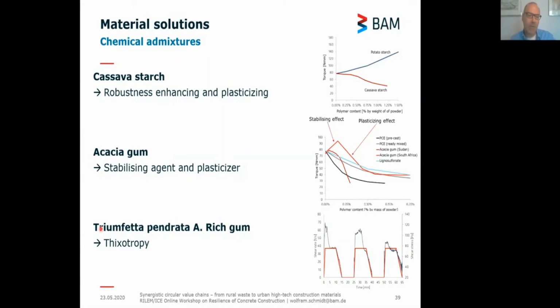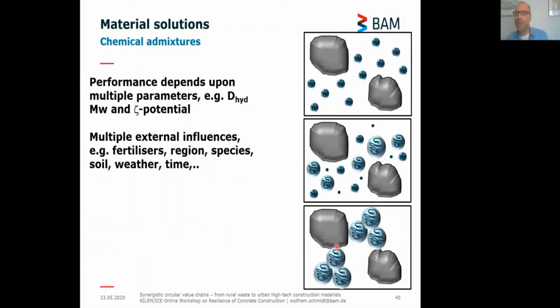And we also found a gum from Central Africa which can dramatically increase the thixotropy, which you can see here. Here you can see the torques at constant shear rate and how it dramatically goes down upon shear. And these materials are so cool that you can make a concrete super liquid for a minute, and a minute later it's stiff. And if you shake it, it's getting liquid again. It's really amazing. So these polysaccharides are extremely interesting, but they're also complicated.